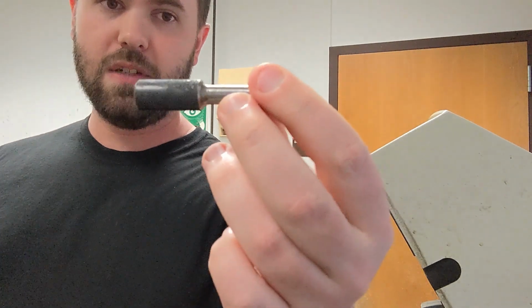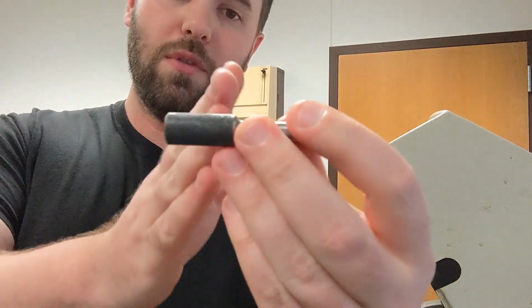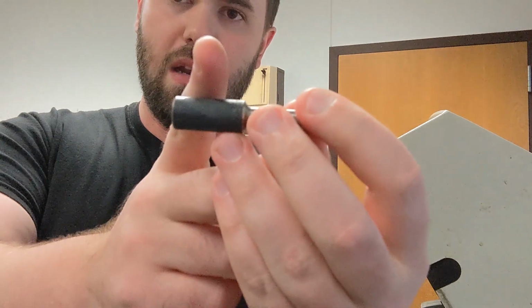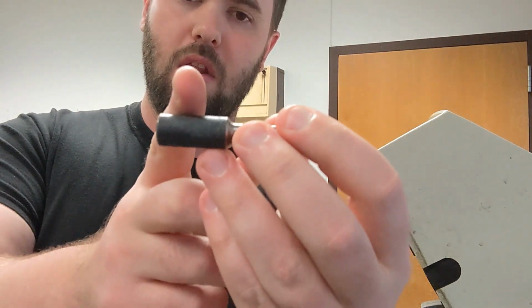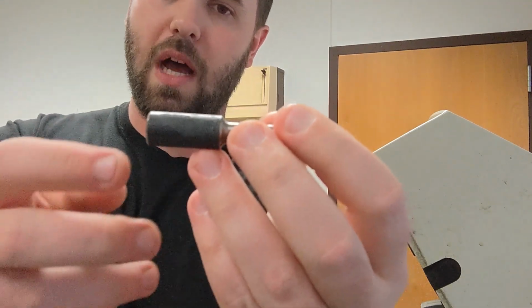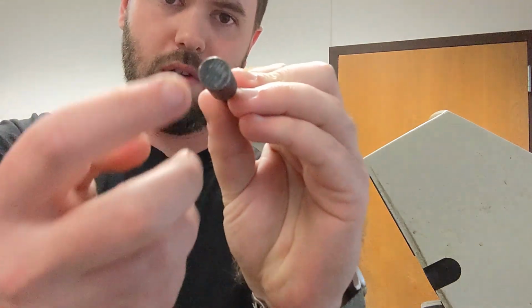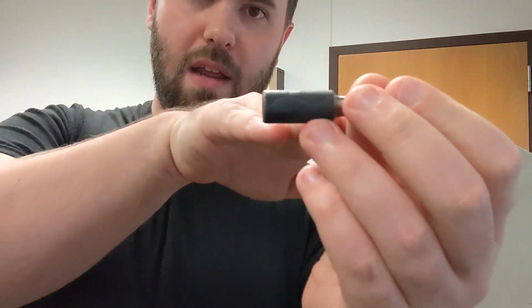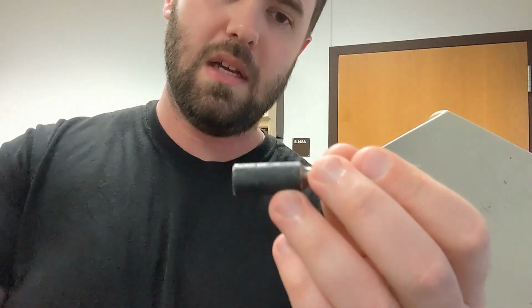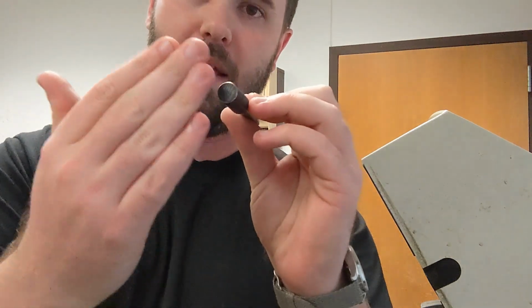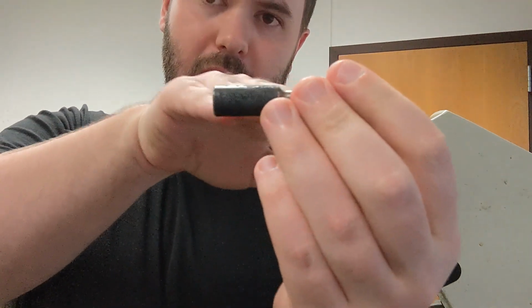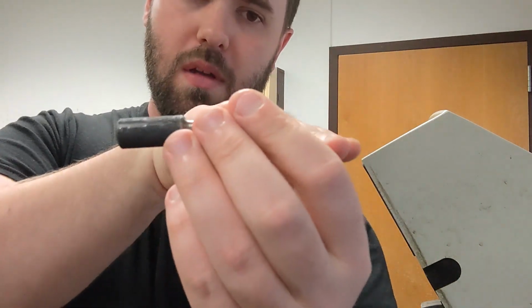So first step is we need to make samples of this. So for these, each of our tensile bars, we're going to cut 2 samples from it, both of which are going to come from the grip side. So the first, we're just going to cut about a half centimeter long grip section. We'll mount it so it is faced this way, so we'll have a circular cross section. And then the second one, we're going to cut it this way, long ways, and we're going to look at the flat face. So we'll have a rectangular cross section. So one, we will be looking at this surface, and the other we will be looking at this surface, going down parallel to the drawn direction. And ideally, we should see a different microstructure, especially for our drawn bars, as they have been pulled during formation. So their grains will be oriented preferentially in the axis of pulling.